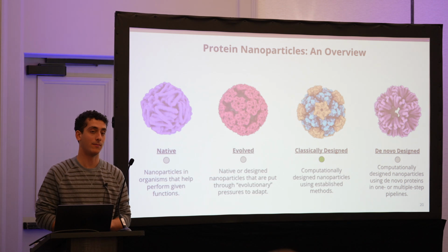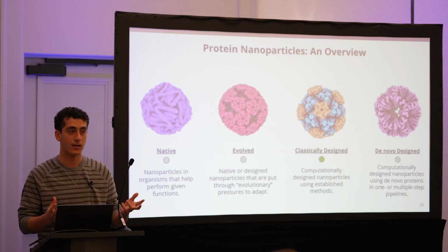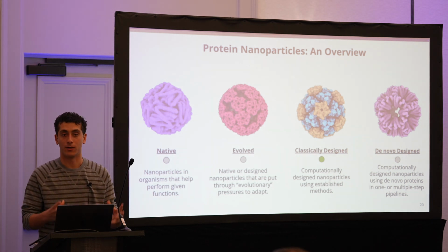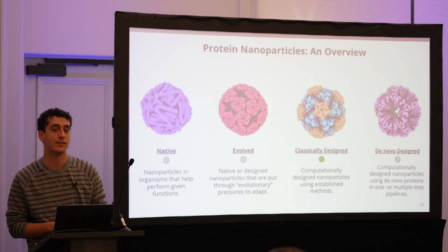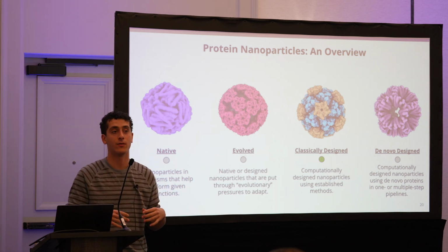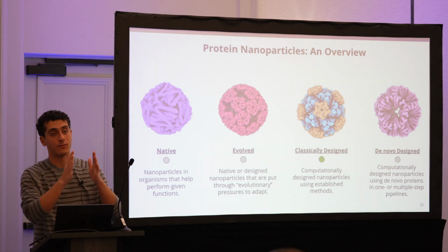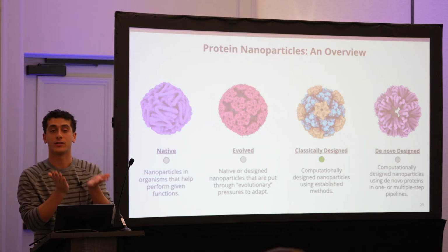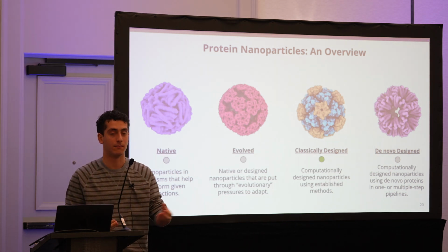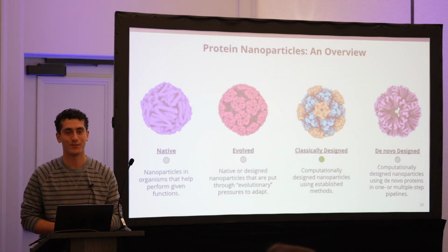So the biggest one that we struggle with is probably stability and long-term stability, making sure your nanoparticle doesn't fall apart after a day or two. I think we've seen that very stable nanoparticles behave very well, but we don't have a lot of very stable nanoparticles. Other things are distance from the nanoparticle to the antigen, so how far spread out is your antigen compared to the nanoparticle, and then how spread out are your antigens from each other. So there are a lot of different factors that you can play with to try to optimize a given problem you're trying to solve. But yeah, there's a lot out there that we're trying to optimize.